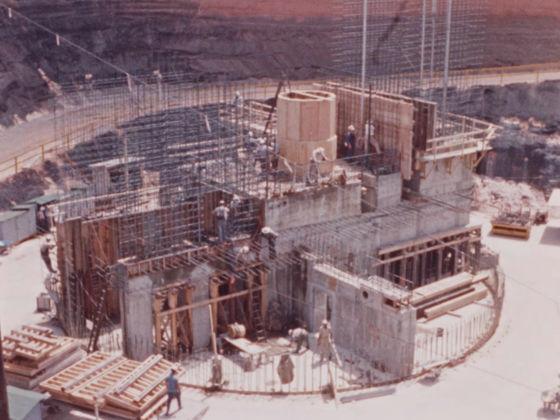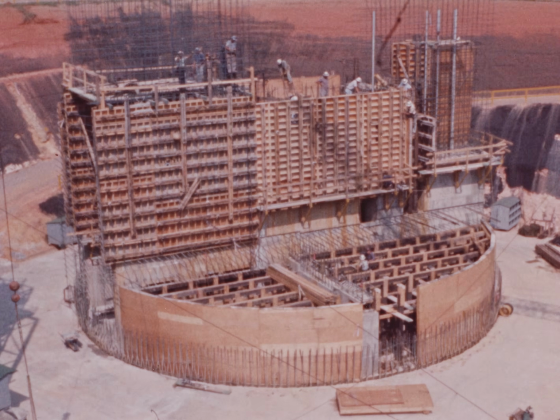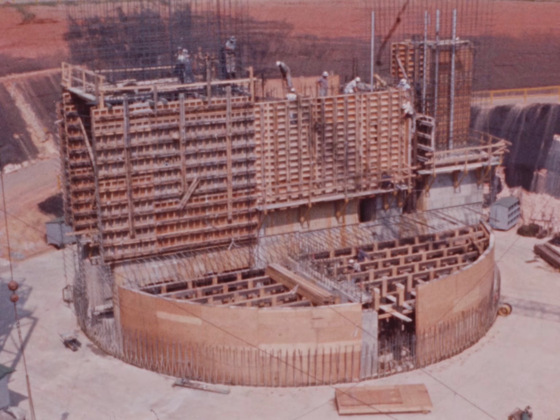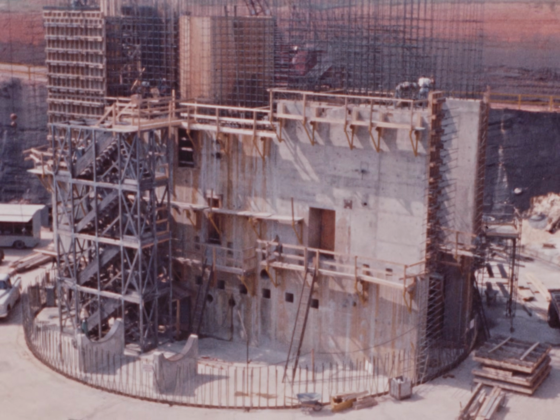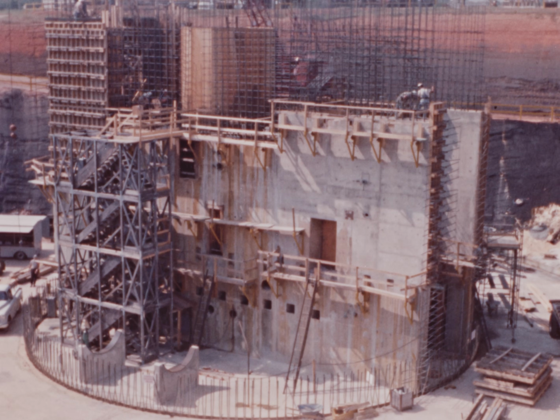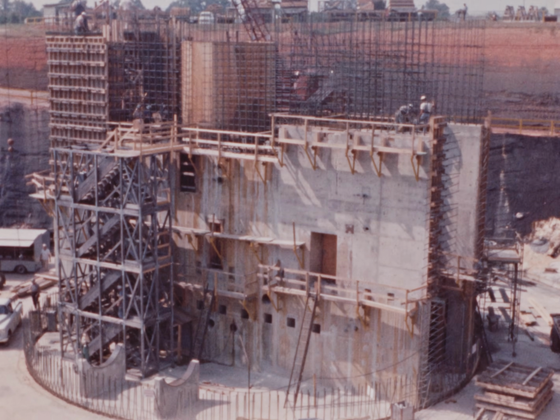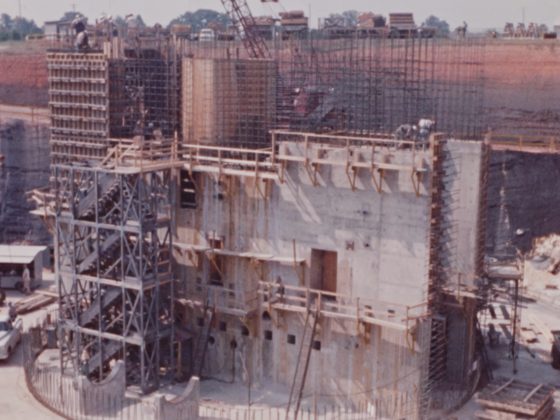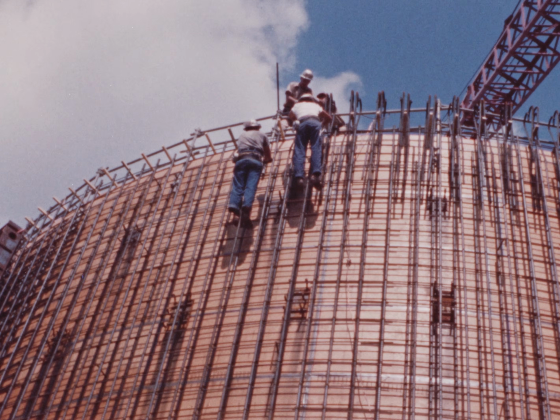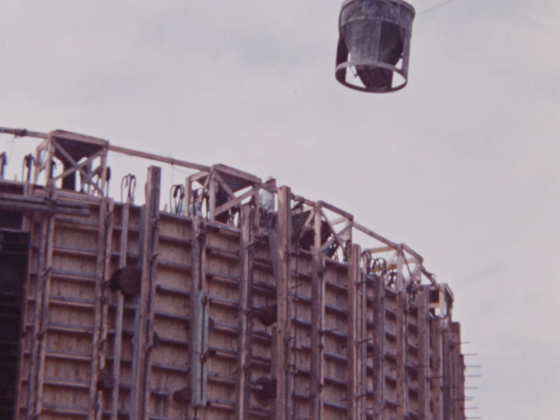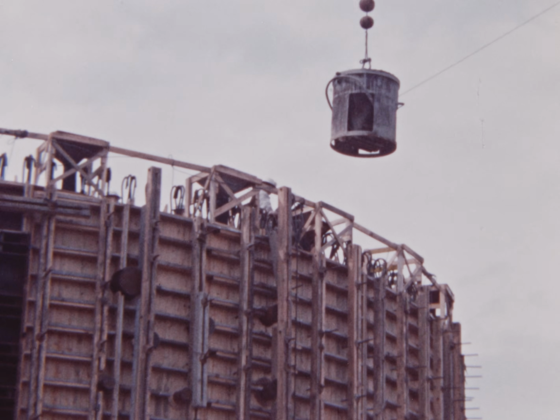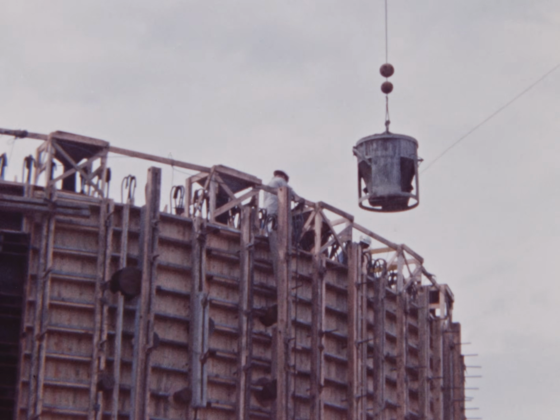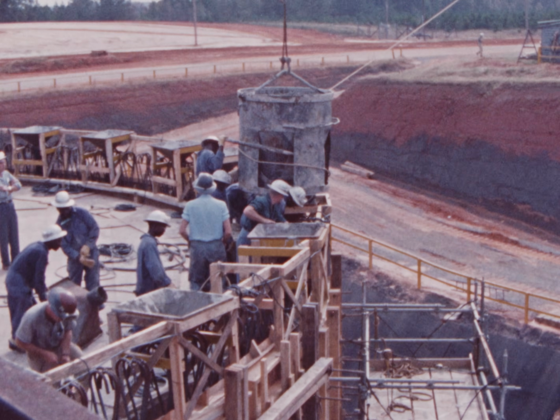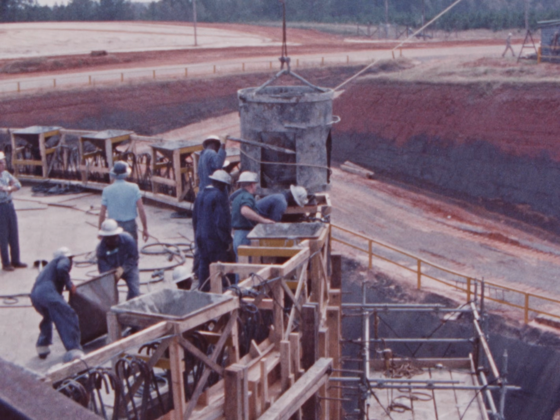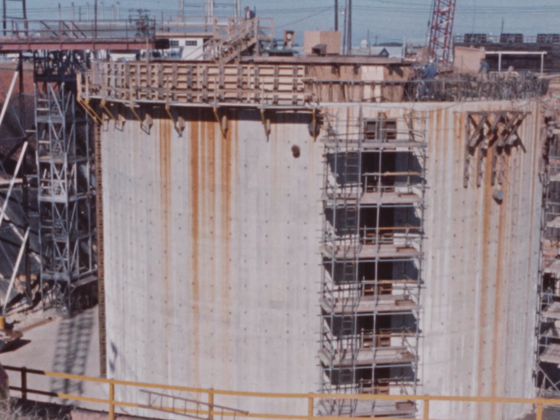The reactor building used a new concept for vapor containment design and construction. Reinforced concrete was used below grade, attached to a carbon steel shell above grade. Its overall dimensions are 70 feet in diameter and 120 feet in height. Tensioned steel strands are used to strengthen the concrete shell against internal pressure. The 18-inch thick concrete shell was placed in one continuous pour.